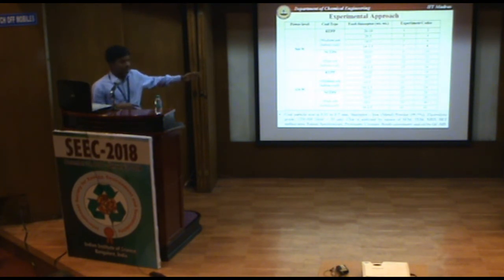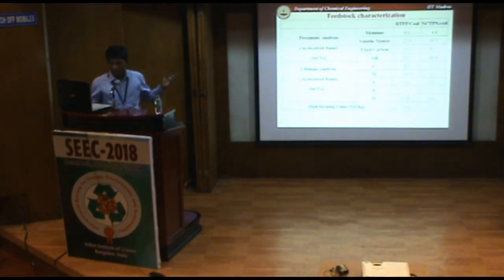Our final temperature is 800 degrees centigrade. So in all these dead conditions, we couldn't reach the final temperature because of the mass present, and the susceptor also, you can see, is a very low amount. So there should be a sufficient amount of susceptor. That's why those experiments actually failed.